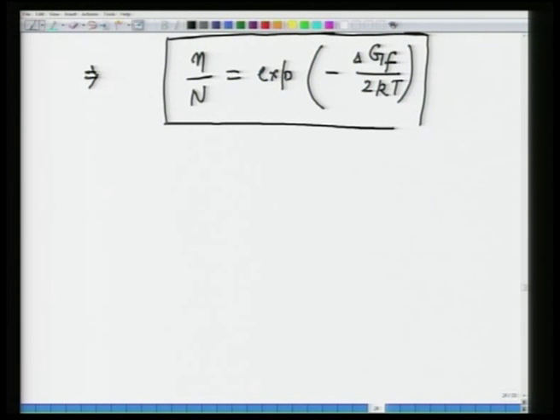So, watch this. What this tells you is that the formation of vacancies is an exponential function of energy expense per pair and temperature. As you can see, as the temperature increases, this number will increase, and as this number increases, this number will decrease. It is going to be much harder to form defects when you have low temperature and higher energy expense.